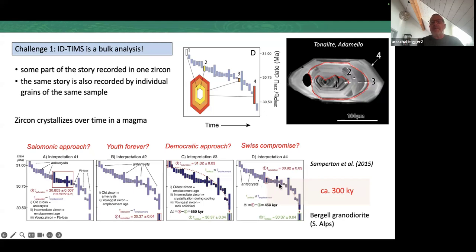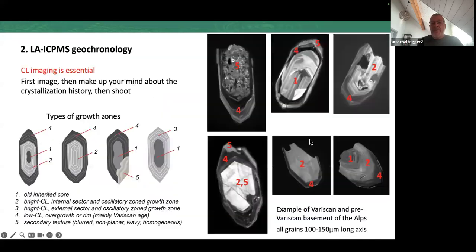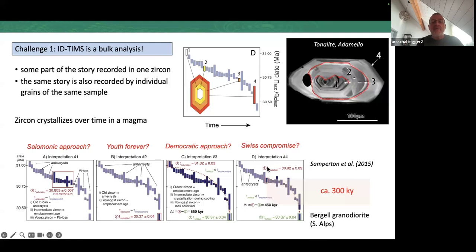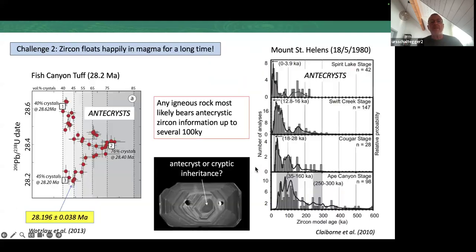So we find some nice Swiss compromise. There is some antecrystic part, and then zircons which kind of reflect a protracted growth, and probably the last one, probably still a grain where we didn't manage to get rid of the lead loss. But it's an interpretation and is purely subjective. So the fact that we have these antecrysts here means, in other words, that zircon is actually happily floating in the magma for quite a long time.